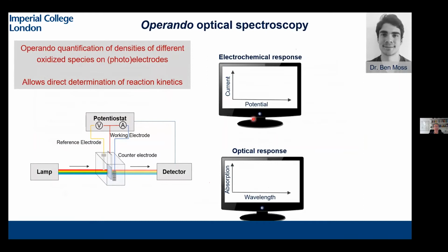The idea here is that we're going to take our electrocatalysts, and these are typically going to be films. So we're not actually studying complete electrolyzers. We're typically studying the electrocatalyst deposited on a substrate. We apply a potential. We start to see a current, which is the water oxidation current. And very often we start to see bubbles. At the same time, we measure the optical absorbance of that electrocatalyst or photocatalyst, most simply in a UV-vis spectrometer. We actually don't use a UV-vis spectrometer.